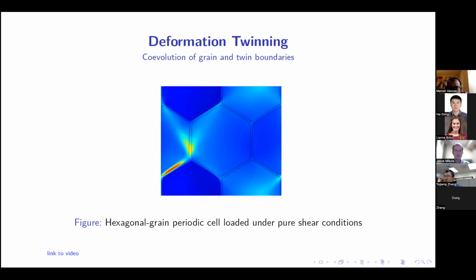And so there is no need for the deformation twinning to be there. So we observe the twinning process and we see that this twin is suddenly disappearing. Eventually all the grains disappear, and we end up with this bicrystal here. These are periodic boundary conditions. Eventually we have curvature-driven grain growth. There is strong curvature here. For very small grains, there would be grain rotation, and eventually we end up with a single crystal.